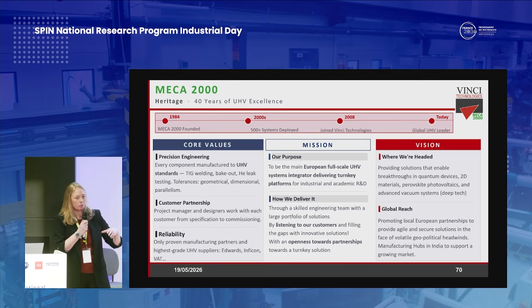we target 3 segments, mostly. There's the renewable energy sector, where we do a lot of systems for perovskites. So these can be standalone equipment, or it can be cluster systems. We have a large cluster system in our lab at the moment, consisting of 4 perovskite growth chambers and a dual cluster chamber for transferring 100 by 100 millimeter samples.